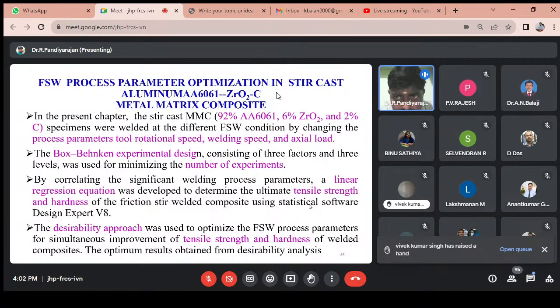The friction stir process parameter optimization in stir casting of aluminum based composite material. The Box-Behnken experimental design, with 3 factors and 3 levels, was used to minimize the number of experiments. By correlating the significant welding process parameters, linear regression equations were developed to determine the ultimate tensile strength and hardness of friction stir welded composite using statistical Design Expert software. The optimization technique and Box-Behnken method to find the optimum solution using desirability approach was used to optimize the friction stir welding process parameters for simultaneous improvement of tensile strength and hardness of weld composites. The optimum result was obtained from the desirability analysis.